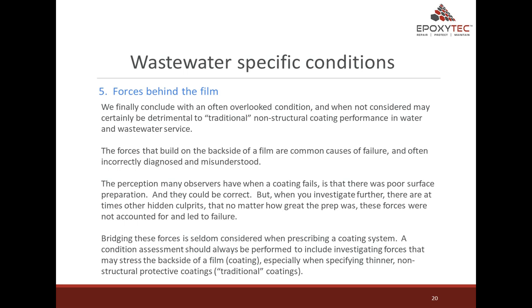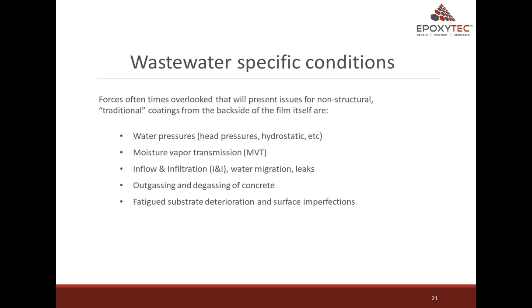The perception many observers have when a coating fails is that there was poor surface preparation, and that could be correct. But when you investigate further, there are at times other hidden culprits that, no matter how great the prep was, these forces were not accounted for and led to the failure. Bridging these forces is seldom considered when prescribing a coating system. A condition assessment should always be performed to include investigating forces that may stress the backside of a film or a coating, especially when specifying thinner, non-structural protective traditional coatings.